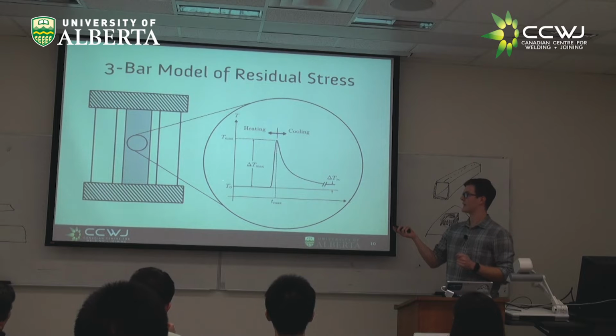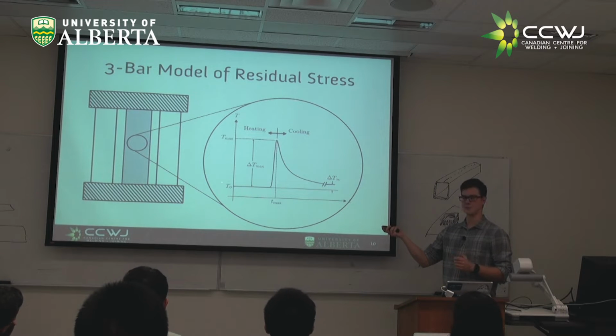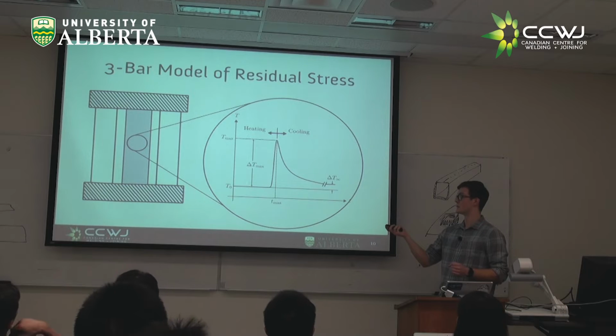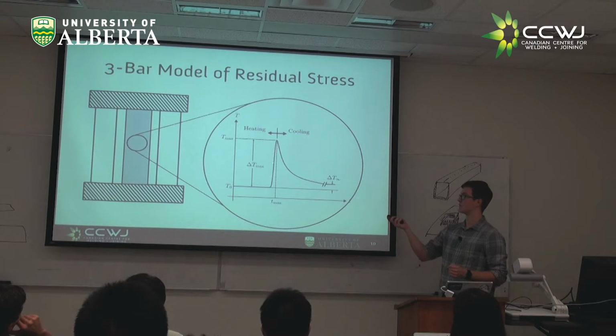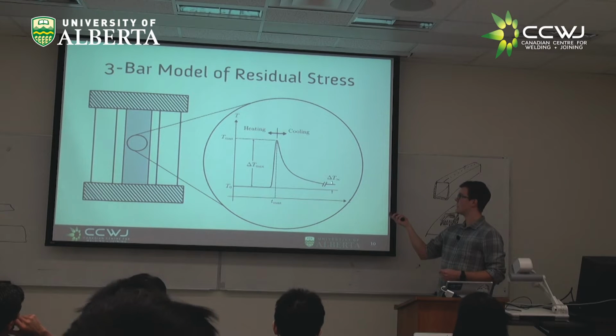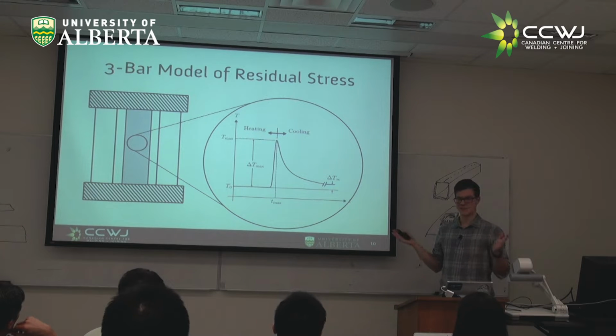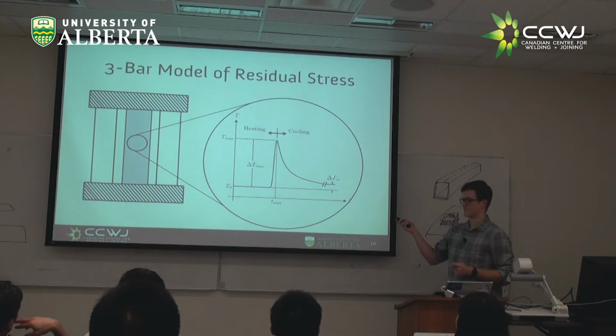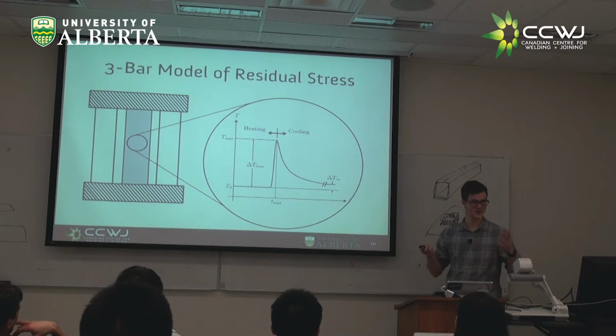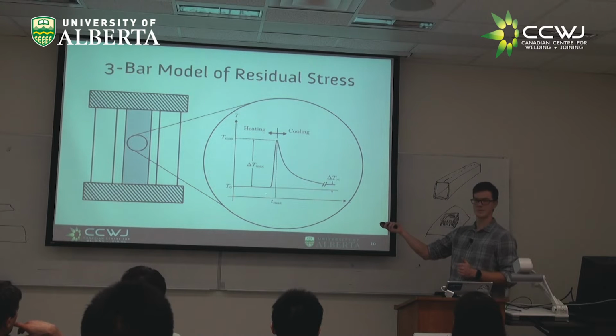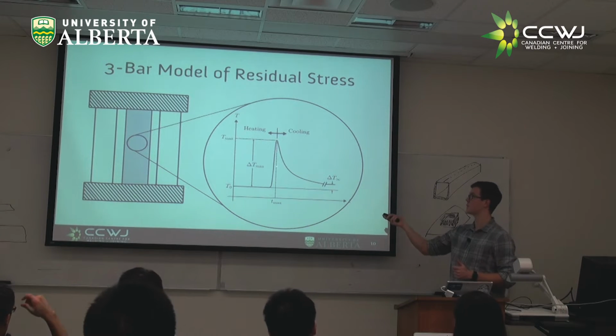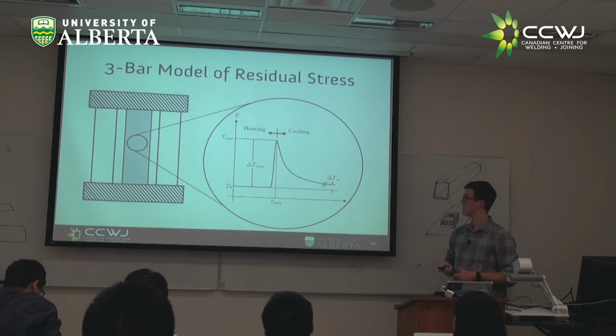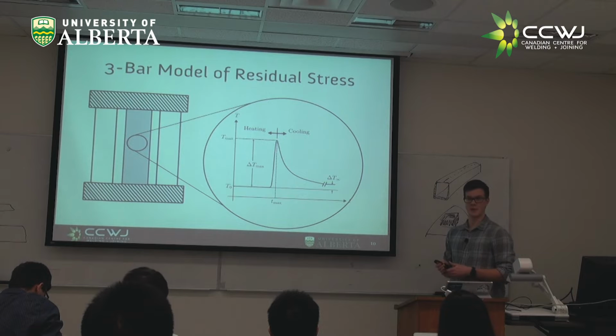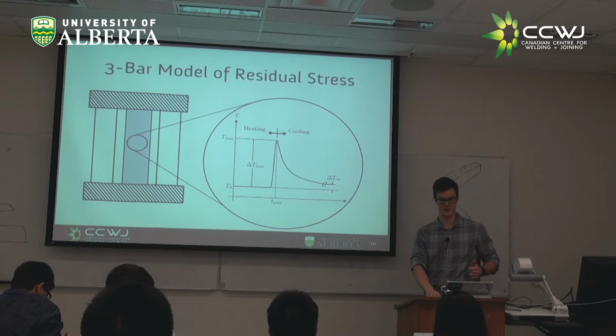So we're going to look at what happens as you start at a point where this middle bar is at some initial temperature T0. We're going to suddenly have heating, where we reach some maximum temperature. And from that point, we cool back to some temperature. Here, I've written the temperature as not T0. In reality, it could be T0, it could not be T0. In reality, you're always going to have some amount of convection in your environment, so it's always going to go back to the initial temperature. But what we're focusing on really here is that we start at some temperature that's the same as the side blocks. We heat to some peak temperature, then we cool back down. And we want to look at what kind of stresses are going to develop and what kind of strain is going to develop as we go through that thermal cycle.